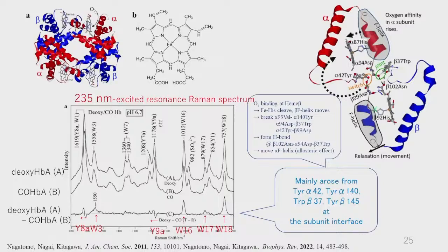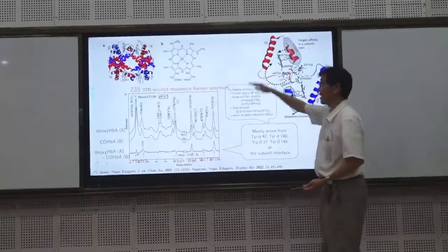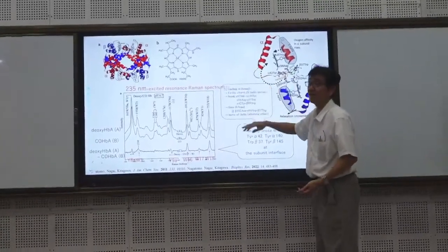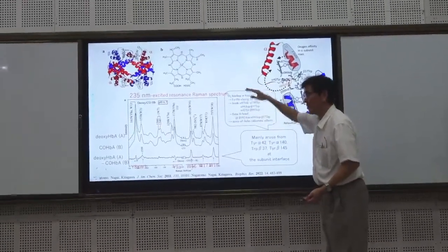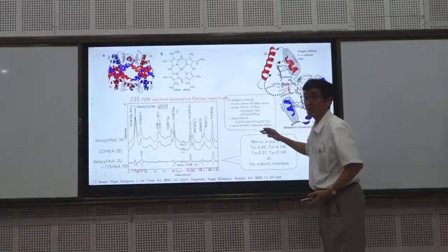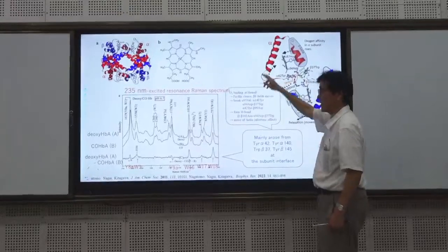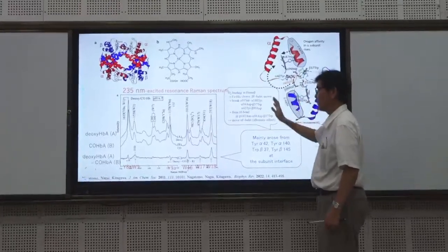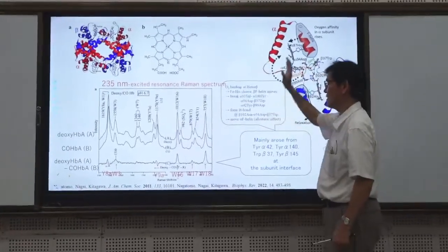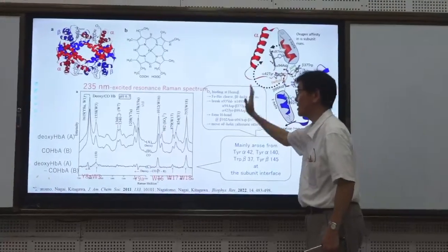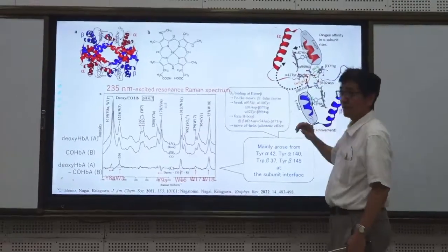By checking the absorption spectrum, you can find the one-photon allowed transition, and that is available for the resonance Raman enhancement. So first we check the UV-visible absorption and identify which chromophore gives which absorption peak.